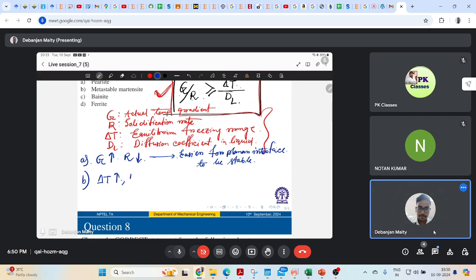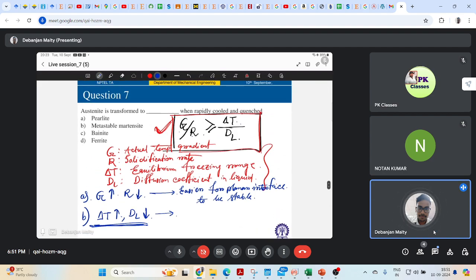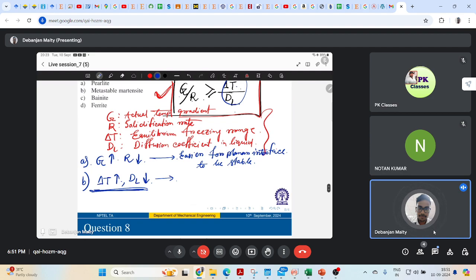and diffusion coefficient is very low. What will happen? For a planar interface to be stable, will this condition be better, or will this worsen your planar interface's stability? So if delta T is getting higher and DL is getting lower, this value is getting higher and higher. This is not easier for a planar interface to be stable at this condition.